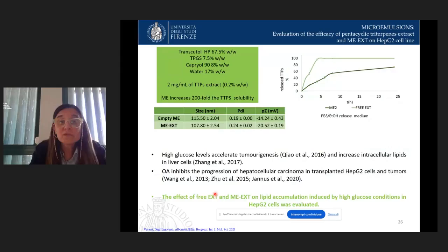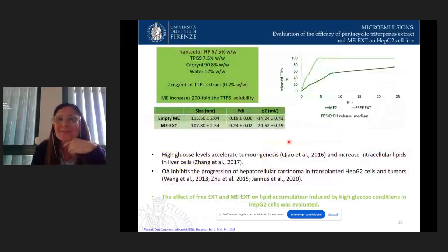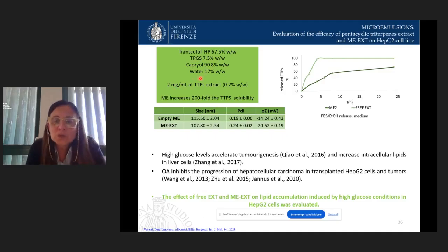We performed many in vitro and in vivo studies with these formulations. In particular, I will show you the results of this study. In this study, we selected these formulations. In particular, this microemulsion is able to load 2 milligrams, to improve the solubility of triterpenes up to 2 milligrams per milliliter. And we tested the extract and also the microemulsions on lipid accumulation induced by high glucose condition in HepG2 cells. High glucose levels, as reported in the literature, promote the development of tumors and increase intracellular lipids. Also in the literature it is reported that oleanolic acid, the main constituent of our extract, inhibits the progression of hepatocellular carcinoma in HepG2 cells.